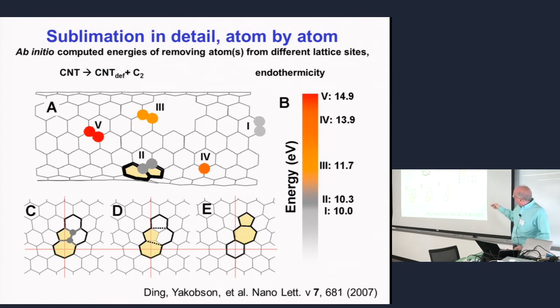But if you evaluate the energy cost, this is the map that you get. This is a colored map. You find that some places are much harder to remove, like from here. You could create a vacancy, but it costs high energy. Some places, like on the edge, are easier to remove, and so on. So you can rank them. And a little bit surprisingly, you find that the easiest place to remove carbon is actually from this 5,7. It's even easier than removing it from the edge. You can remove it from this 5,7, and why? Why is it so energetically cheap from this particular location?